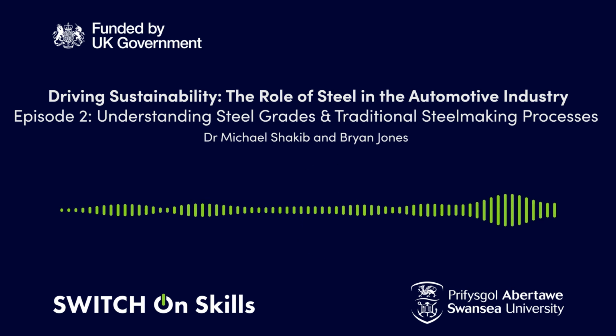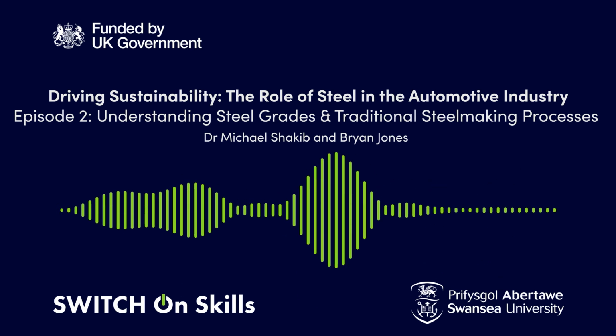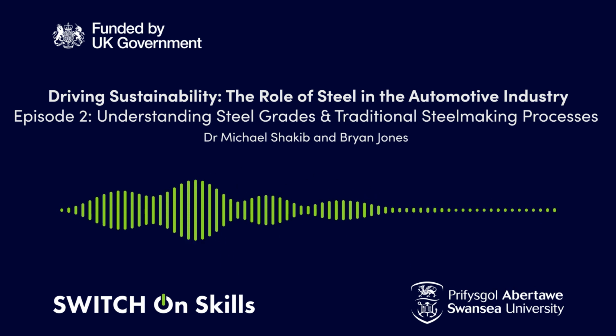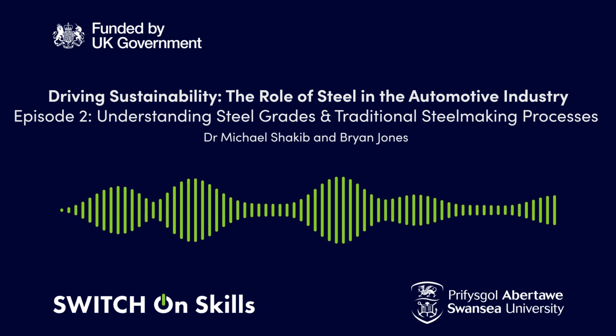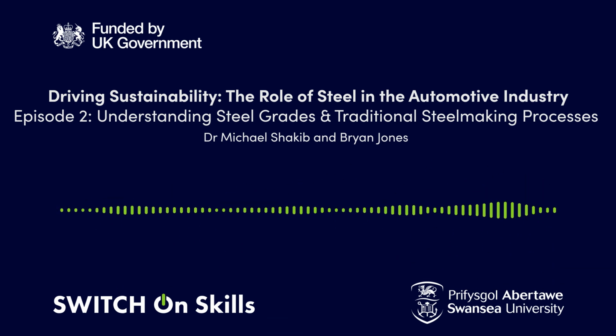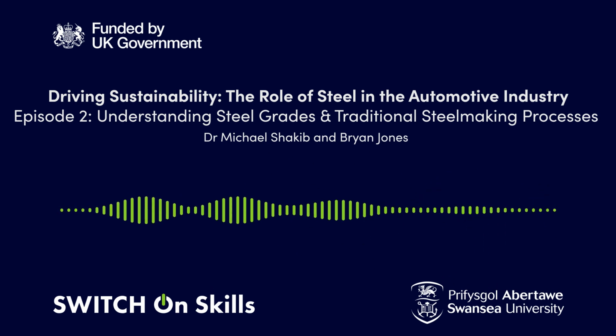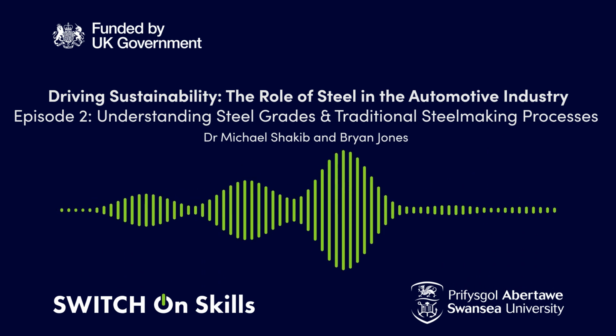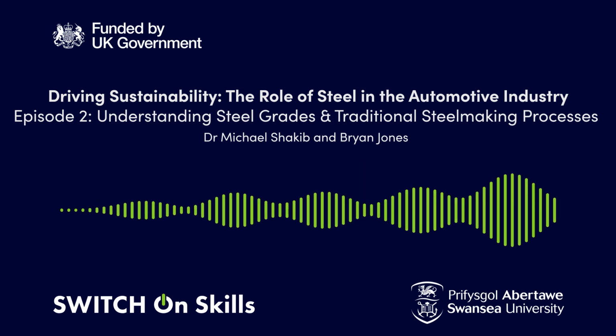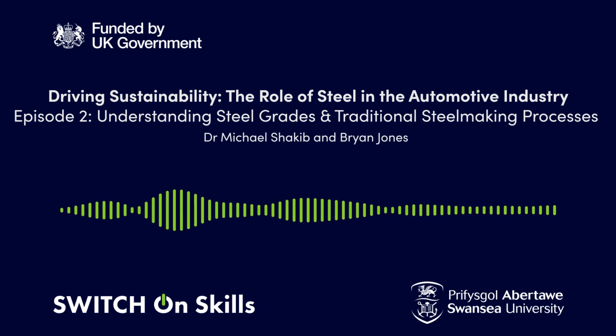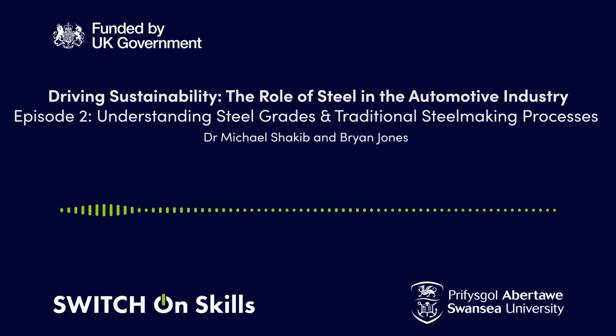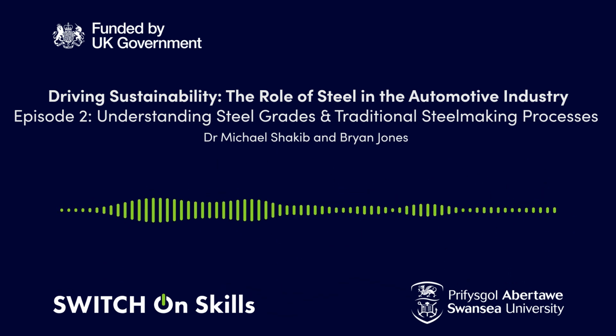Yeah. The Corex process is different. You're using coal, and it's got 2 elements to it. So you've got your shaft furnace and then a bottom reducing furnace. From the reducing furnace, you generate carbon monoxide by injecting oxygen, as in the BOS process, and carbon. So you've got carbon converted to carbon monoxide, which is then transferred from the reducing furnace to the shaft furnace above it to act as the reducing agent. That produces quite significant levels of carbon, so you're talking about 4% of carbon or more, together with a significant level of impurities. So these DRI reduction processes convert an iron ore to a usable product for the electric arc furnace, but nevertheless, the level of impurities is significantly greater than from the BOS process. Oh dear, still. Yeah, still.